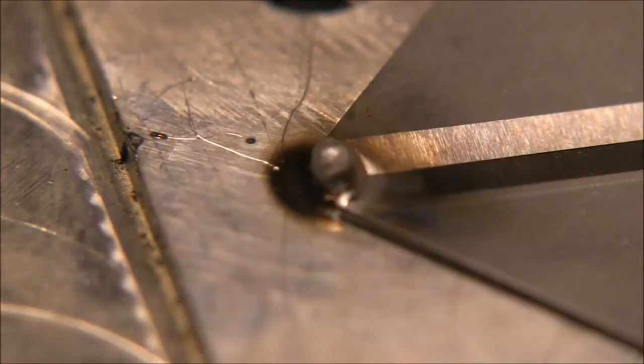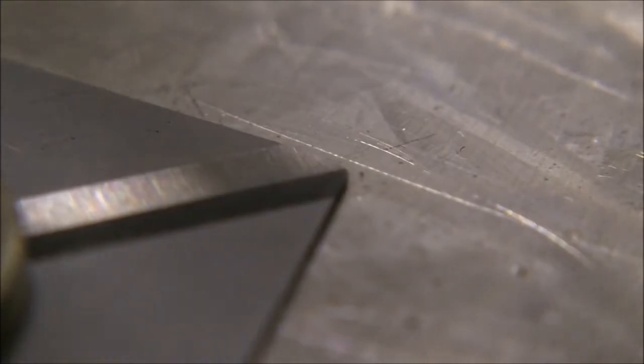What we'll do now is we'll look at the other end, and I'll try to light up on that using the blunt tapered electrode where the grinding scratches go sideways. And again, not a crisp start. Arc wandering off the side of the electrode off one of those scratches before it ever goes to the tip. I've got to get it up to about 10 amps before the arc ever comes off the tip and is accurate.